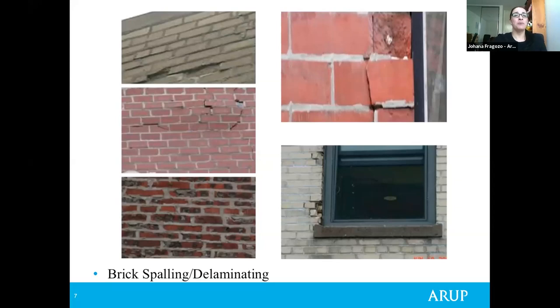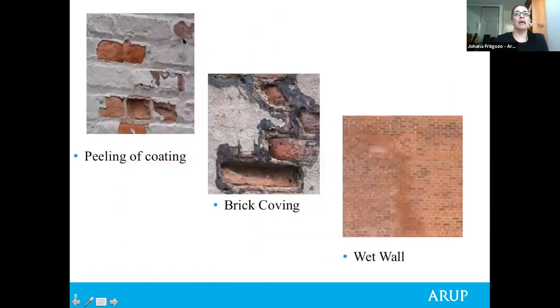Then we have peeling of coatings. If the brick wall has a coating, this could potentially be due to inadequate material selection, the presence of non-breathable coatings, and moisture accumulation, due to the presence of the coating that does not allow enough vapor permeability.